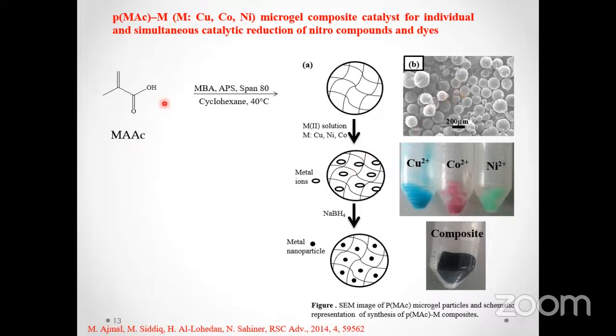Methacrylic acid contained the carboxylic group. This carboxylic group was first deprotonated by treating with a base, and then it was exposed to the copper ions, cobalt ions, and nickel ions. And the absorption of nickel ions, cobalt ions, and copper ions can be seen from the change in the color of the hydrogel.